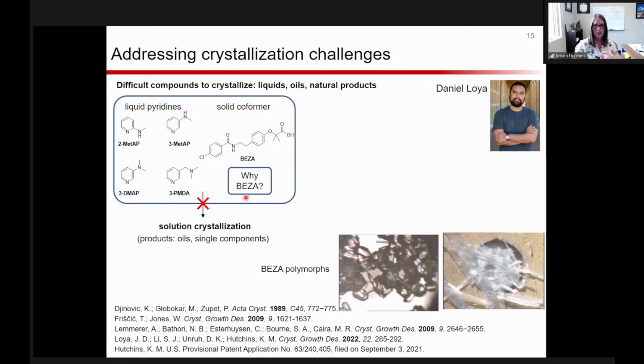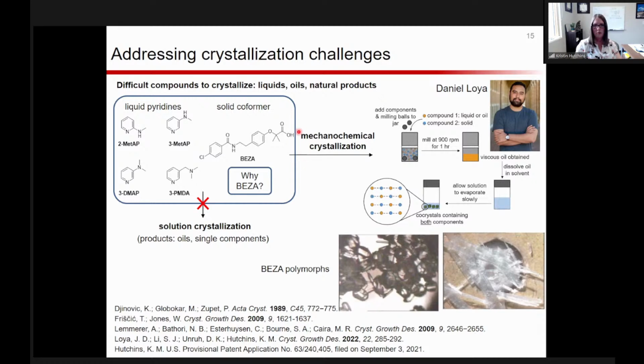And so what we decided to do was turn to mechanochemical milling. We added those two components to our milling jar, so just neat, with no additional solvent added. And we milled those at 900 RPM for a period of an hour. And after this milling step, we obtained a viscous oil.